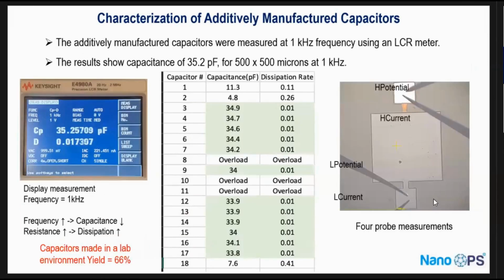So what about yield? All this is done in a lab. There's no clean environment, no cleanroom inside the fab. In this case, we looked at 18 capacitors that were made. There were no shorts. These are 500 micron by 500 micron, and what we're looking for is an average of about 34 picofarad. Our yield was based on the ones that did not meet the spec, which means overload, higher than the 34 that we're looking for, and the ones that came out lower. The yield is about 66%. This is not optimized at all, and also the tolerance for those was very low, less than 3%.